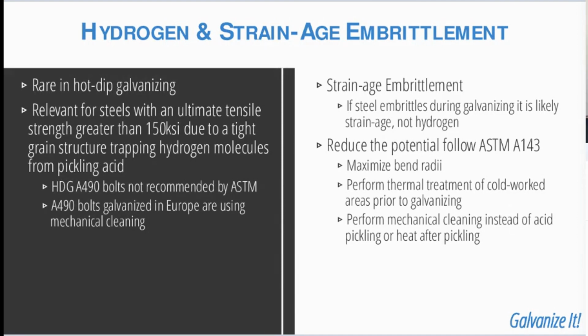Drill if possible, or if punching is necessary on steels that are 3/4 inch or greater, you can ream at least 1/16 inch around the edge of the hole. In general, we want to try and avoid excessive cold working, but if needed, a thermal treatment can be used to relieve stresses prior to hot dip galvanizing in order to avoid strain age embrittlement.